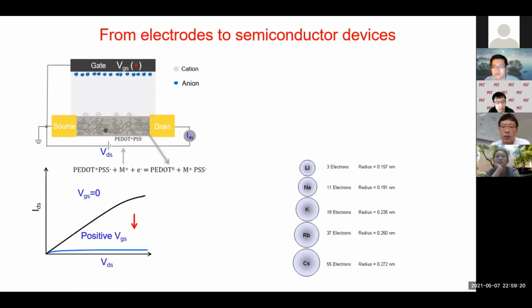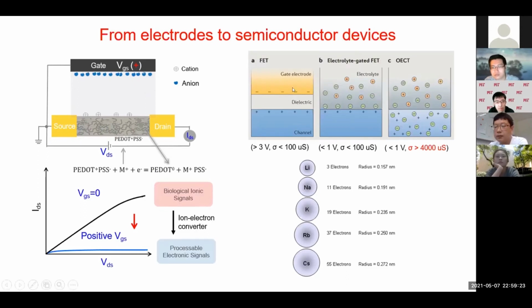Okay, compared to other devices, for example, field effect. Field effect device is a device used mostly in computers. For example, CMOS, right? The CMOS device is silicon-based. First of all, the dielectric is not electrolyte. There's no ions. At least they don't use electrolyte or something. So first of all, it does not play very good with ions. It's a dielectric. You polarize the dielectric, and then you have some surface charges induced here, very thin channel, 3 nanometers, and then you induce a channel here, so become conductive or not. But of course, you see, yeah, I can replace this dielectric with electrolyte, right?